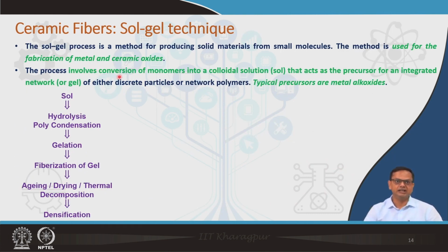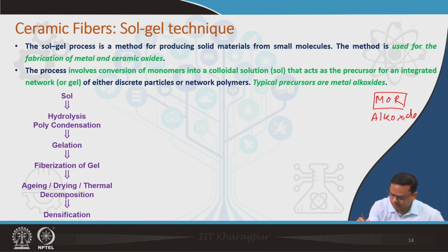Sol gel technique, as I was mentioning earlier, is a process used for fabrication of metal and ceramic oxide, and it involves conversion of monomers into colloidal solution, which we are calling sol. So, the precursor material in the earlier case I mentioned was MOR, which is basically an alkoxide. You choose a certain solvent in which the alkoxide is dissolved to make a colloidal solution, and this colloidal solution goes through hydrolysis and polycondensation reaction. I will show you again, and that forms a network of gel.